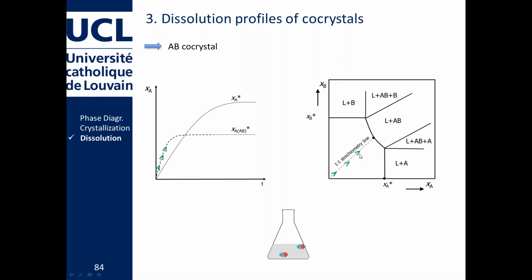Okay, the amount of caffeine is given by my x-axis. This will continue, of course, up until the point that I reach the solubility line of my co-crystal. Then my solution, that last co-crystal is in excess, it won't dissolve. And as you can see now, my concentration of caffeine is actually lower than the solubility of caffeine. So you reached a concentration of caffeine with your co-crystal which is lower than the concentration of caffeine on its own.